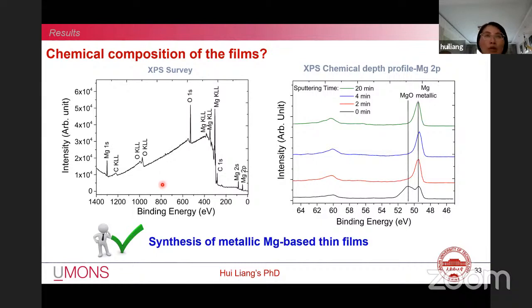And then we use argon to sputter the Mg film. After 2 minutes of sputtering, the depth is about 40 nanometers. The MgO peak completely disappeared, while the peak intensity of Mg strongly increased. So both these observations clearly confirm that the deposited film is only oxidized on the top surface of the film, suggesting Mg films have been prepared successfully.